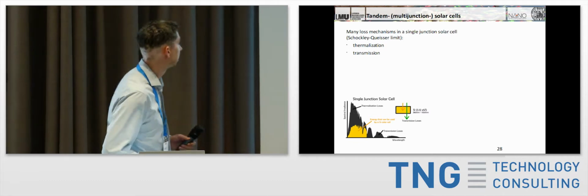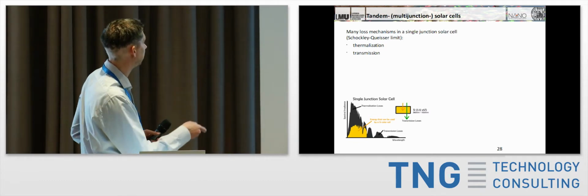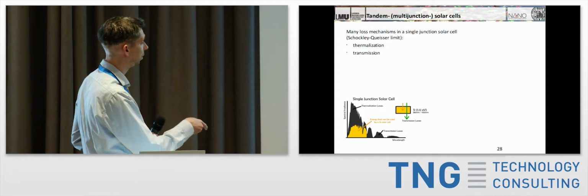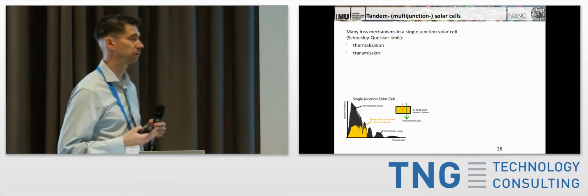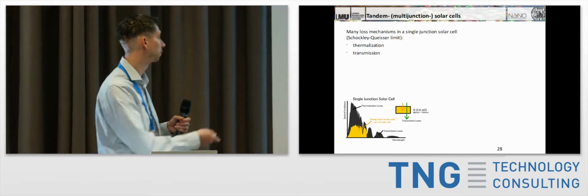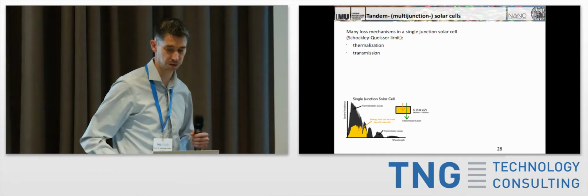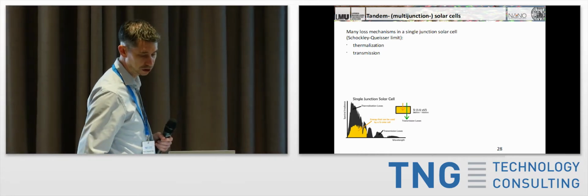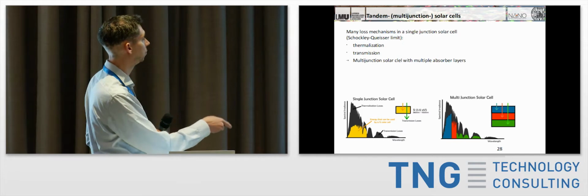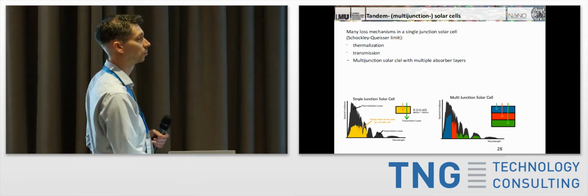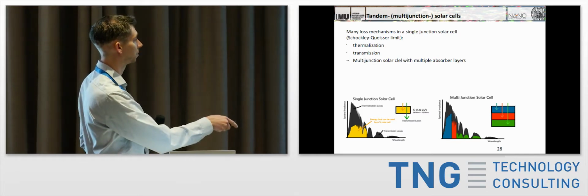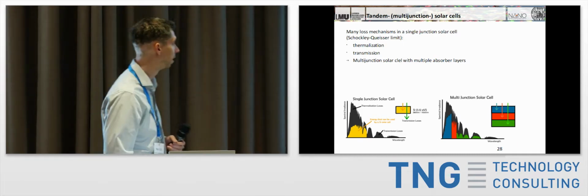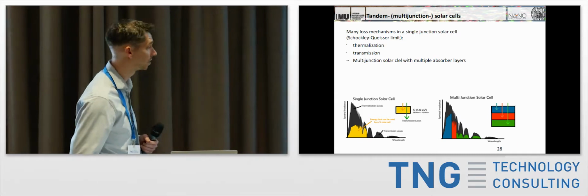So tandem solar cells, I told you the idea essentially that in the single junction solar cell we can only really use a small part of the light, because either the photons have not enough energy and aren't absorbed, or they have too much energy and all of this is lost due to thermalization. But you can actually overcome that with a strategy that if you, instead of using a single absorber layer, start to use multiple absorber layers that are tuned to different parts of the solar spectrum, because now they can absorb a different amount of light and transfer a different amount of this energy actually into